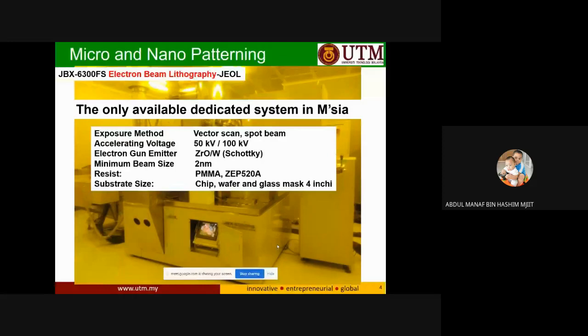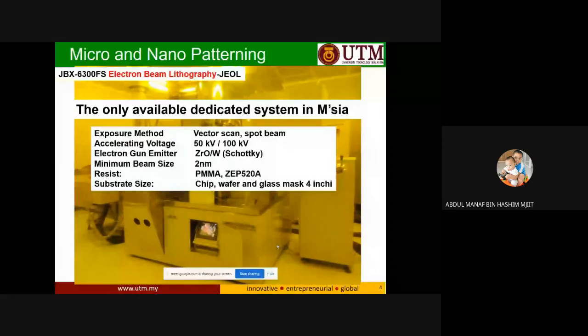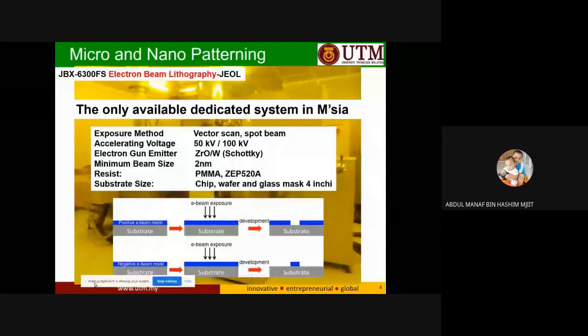Okay, I think this one is just to introduce what electron beam lithography is. Basically, on the substrate, we put a resist, and then we expose it with the electron beam. So we write the pattern, and then we proceed with the development, and then you get the pattern. After you get the pattern, we can proceed with either metal deposition or etching to get the final pattern.